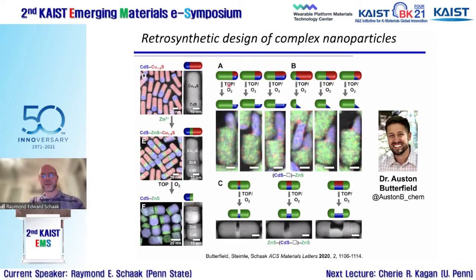Another one is tuning the exchange length and combining that with being able to etch out the copper sulfide, which is a known reaction, to control the length of cadmium sulfide protrusions that emerge from an otherwise zinc sulfide particle, either these more flat protrusions or ones that are more pointy, based on how the interfaces want to be, based on cadmium sulfide and the crystallographic relationships,